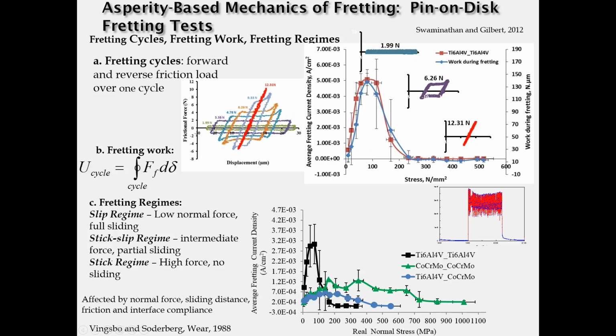Also shown in this plot are the three materials, titanium, cobalt chrome, and the mix, showing the fretting currents and their variation with the contact stress. And you can see each is very different from the other, with the mixed alloy actually giving the lowest fretting corrosion currents of the three different possibilities.